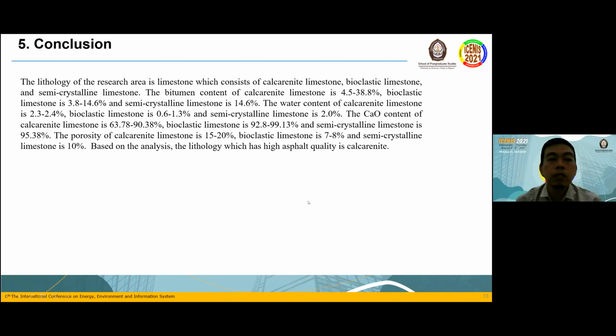Conclusion. The lithology of the research area is limestone, which consists of calcarenite limestone, bioclastic limestone, and semi-crystalline limestone. The bitumen content of calcarenite limestone is 4.5 to 38.8%, bioclastic limestone is 3.8 to 14.6%, and semi-crystalline limestone is 14.6%. The water content of calcarenite limestone is 2.3 to 2.4%. Bioclastic limestone is 0.6 to 1.3%, and semi-crystalline limestone is 2.0%.